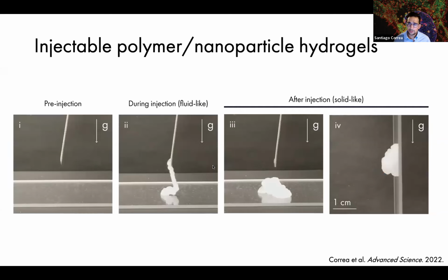And so here are some pictures of us injecting these materials through 21 gauge needles. You can see their shear-thinning and self-healing properties in these images. So for example, as we apply higher shear forces during injection, the material behaves as a liquid and extrudes through the needle. But after injection, those interactions between the nanoparticles and the polymers reestablish themselves and rapidly regenerate a solid material that can resist moderate forces like the force of gravity.